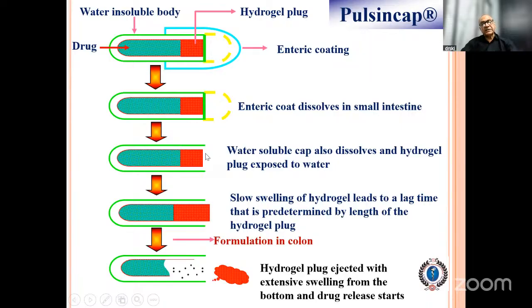When the small intestinal fluid comes in contact with this plug, a hydrogel plug or plug of gums, it will start swelling slowly. The swelling of the hydrogel leads to a lag time that is predetermined by the length of the hydrogel. So at what time it is supposed to be expelled, we have to monitor. We design it in such a way that when this system reaches the ileocecal region, the plug will be expelled out due to swelling. By that time your capsule body will reach the colon and release the drug. So this is how Pulsincap works.